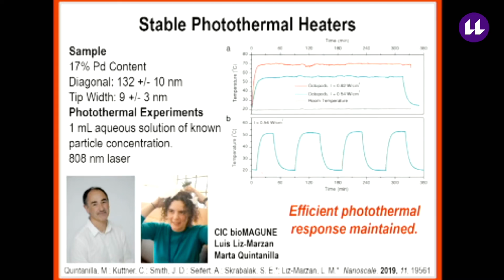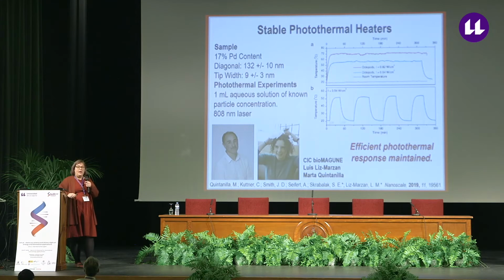So this actually prompted a collaboration with Luis's group, and I had the great pleasure of working with Marta, who gave a talk yesterday. This was part of my sabbatical, where we decided to look at the photothermal properties of these gold palladium nanocrystals. The experimental setup was actually quite straightforward. The nanocrystals are just dispersed in water, and we're irradiating the nanocrystals with a laser that overlaps well with their LSPR, and we're tracking then with a photothermal camera how the heating profile of the water changes.